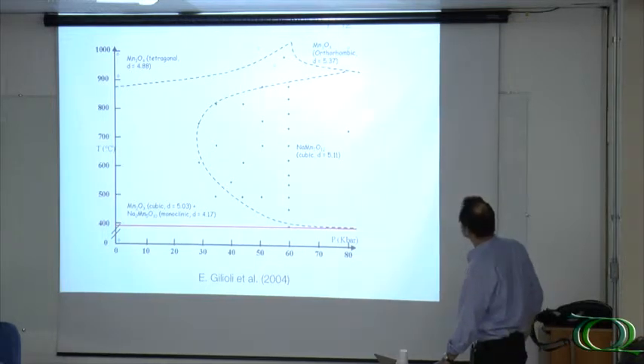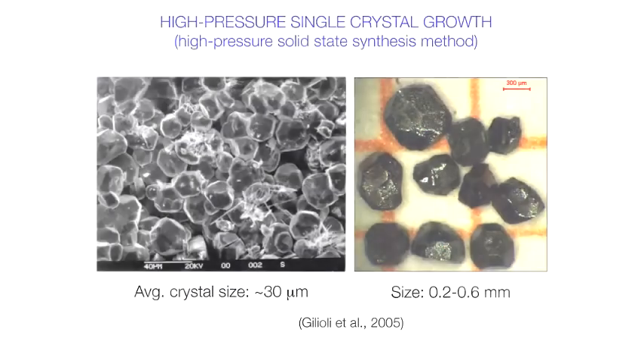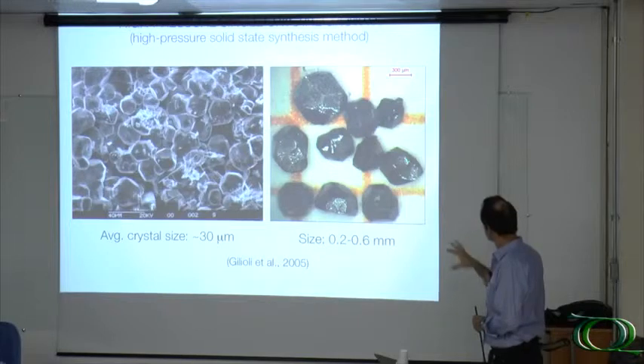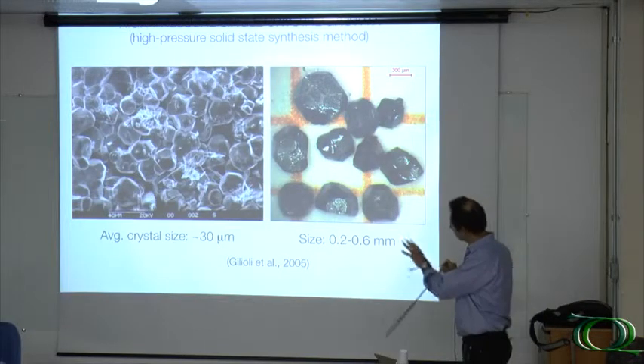This gives you an idea of the various morphology. You can obtain single crystals up to 0.5 to 0.6 millimeters until now, and powders depending on the growth conditions. You have bigger crystals when you are near the phase decomposition.